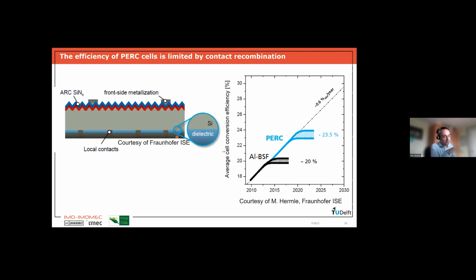And this is a graph that you will see coming back. So it's a kind of roadmap for the industry or for the different cell concepts that was made several years ago by Fraunhofer ISE. So what this map shows is that the average cell conversion efficiency in the industry is foreseen for aluminium BSF to sort of stabilize around 20%. And for PERC, the prediction is that probably we can go close to 24% with average cell efficiencies in industry. So these are not champion cells. Champion cells can be higher, but in industry.